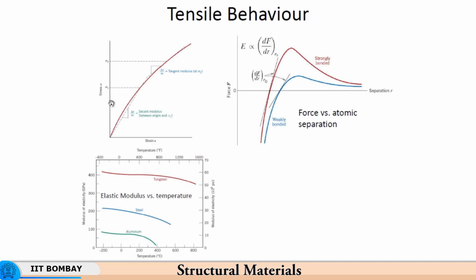Here you see that the temperature affects the elastic properties. You have tungsten, which has a very high modulus of elasticity, and it is retained at high temperatures, and that is the reason why it is used for high temperature application. So it is called a refractory alloy, whereas steel and aluminum are not so good in resisting temperature when it comes to the Young's modulus. Aluminum has a low Young's modulus which diminishes very rapidly with temperature. So this is a good material for hot working or high temperature deformation, whereas tungsten is a good material for high temperature structural applications.